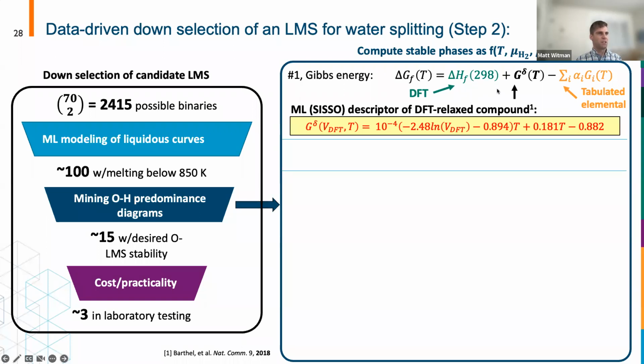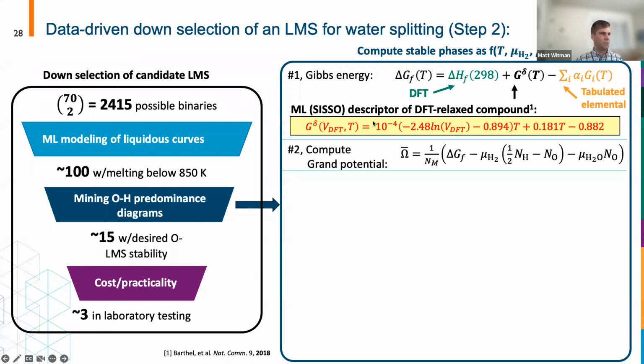So you perform a DFT calculation, you use this remarkably simple correction factor for a given compound, which just relies, for solids, on the volume of the DFT relaxed cell at a given temperature, and that gives you this correction that, when normalized for the elemental Gibbs free energies, you get the Gibbs free energy of formation of that compound. So if you can measure that, then you can compute the grand potential.